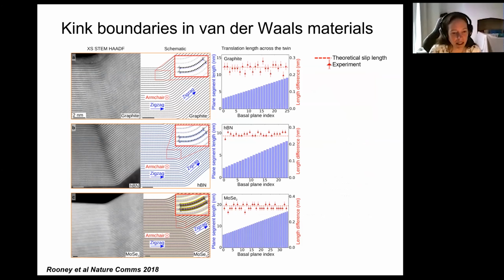And what he did was he very painstakingly measured the length of one lattice plane compared to the next lattice plane, because that can tell you what the change in stacking is between one layer and the next, or between one side of the crystal and the other. And what he found was that throughout these layers, there was a very consistent difference in the stacking. And this difference in stacking, which is measured here, corresponds to a known slip distance within the crystal.